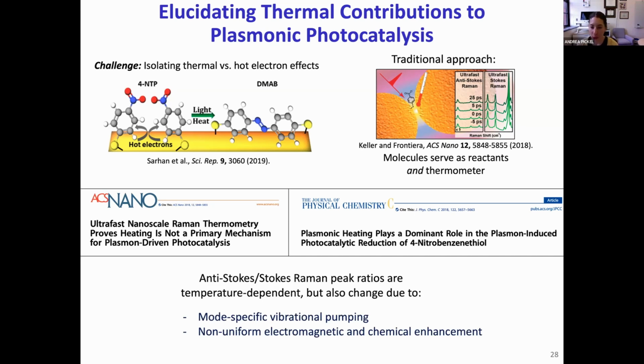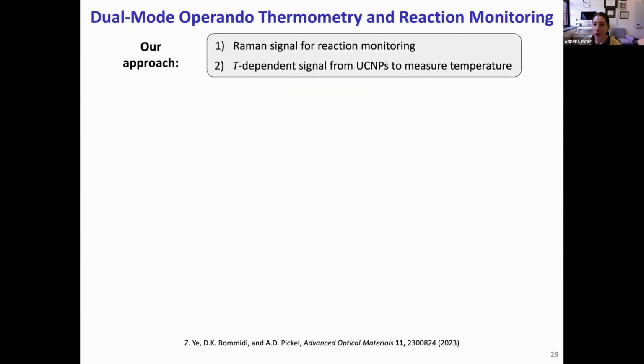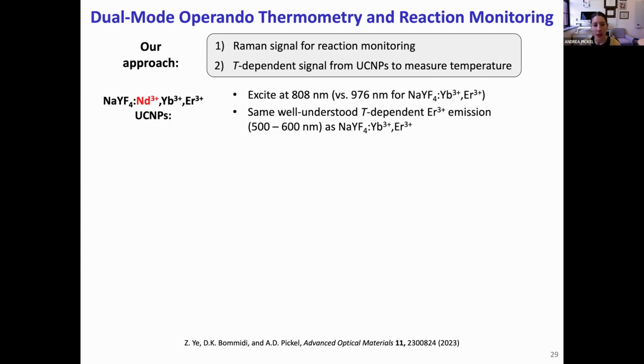One potential reason for these discrepancies is that while Raman peak intensity ratios do depend on temperature, there are also other non-thermal factors that can change these ratios, particularly while a reaction is occurring. So our approach is that we still use Raman spectra to monitor the chemical reaction, but to measure temperature, we instead use the temperature-dependent luminescence emitted by UCNPs. We can use a single 808 nanometer laser to both photocatalyze the chemical reaction and excite our UCNP thermometers, which is made possible by using ytterbium and erbium-doped UCNPs with an additional neodymium dopant.